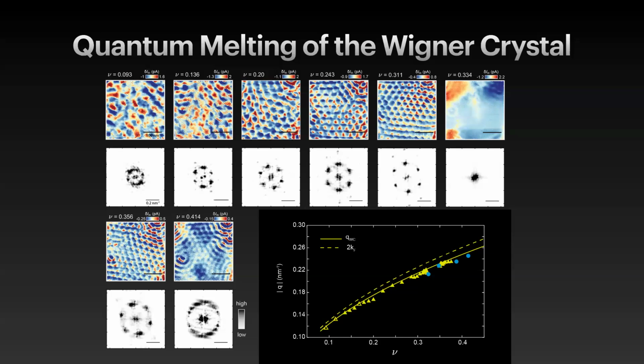And it could be that we cannot measure between the two blue dots here because we're really in the incompressible state, where we are in the blue dots, we are on the plateau, but away from the incompressible state. So it's not a feature of the lock-in state, it's a feature of something near. No, an off-phase state will have this feature. I see. That's what those papers talk about. Okay. Actually, they start with basically the fractional Hall. It's actually a kind of a beautiful paper.